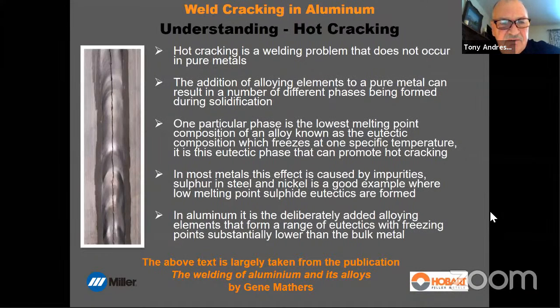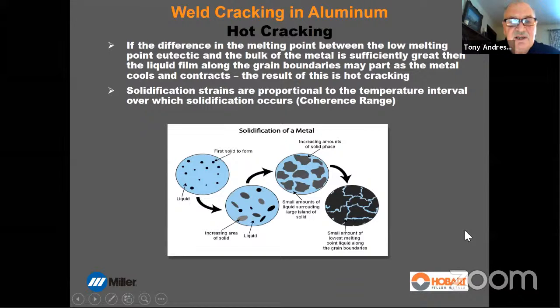All aluminum alloys have a certain susceptibility to hot cracking because they're all alloyed, apart from pure aluminum, of course, but any of the alloys are susceptible, just varying degrees of susceptibility. So it's all about how the material goes from liquid to solid and what is left in these grain boundaries at the end of solidification. If we have these eutectics along the grain boundaries, these low melting point components, then they tend to rip apart during solidification from the shrinkage stresses, and that's when we get hot cracking, all right?